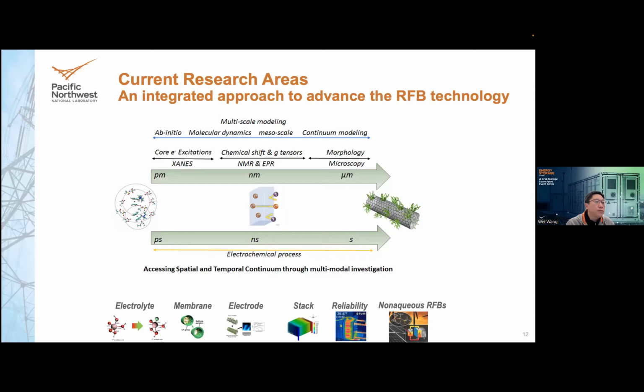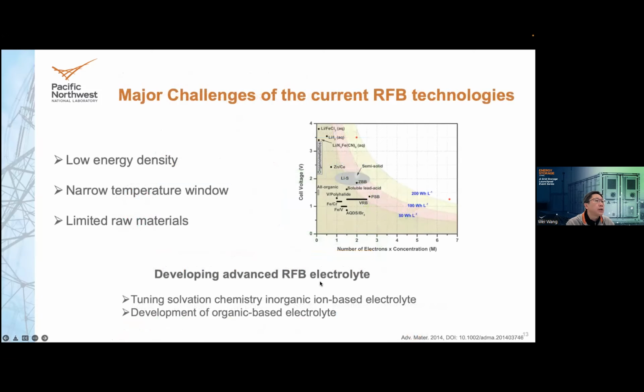So what are the major challenges we need to deal with on the redox flow battery? One issue is the low energy density. You're probably already aware of this. This is a figure showing the energy density of most of the redox flow batteries. Most of them, for the redox flow batteries that have both liquid anolyte and catholyte, are actually lower than 50 watt-hour per liter, definitely lower than 100 watt-hour per liter.